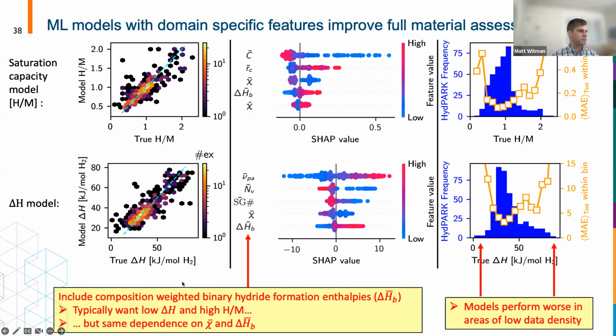Some few things I want to highlight is that we've included domain specific features that have improved these models. So things like the composition weighted mean of the binary hydride formation enthalpies improves your property prediction significantly. But you can also see that these properties are codependent on a lot of these properties. So the similarities that you see and the feature dependence basically mean that as H to M goes up, so does delta H. But in general, we want those things to be oppositely correlated for optimal materials. We want a low delta H, but a high hydrogen to metal ratio.